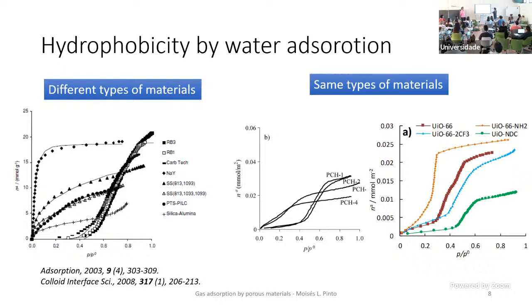Even for more recent materials, in this case I give some examples of MOFs, different ones. For instance, the structure is the same. We are going to talk a little bit about one of these materials, UiO-66. You are going to see the structure. But we can decorate the pores with different groups, and you see that we also change the hydrophobicity of the surface.